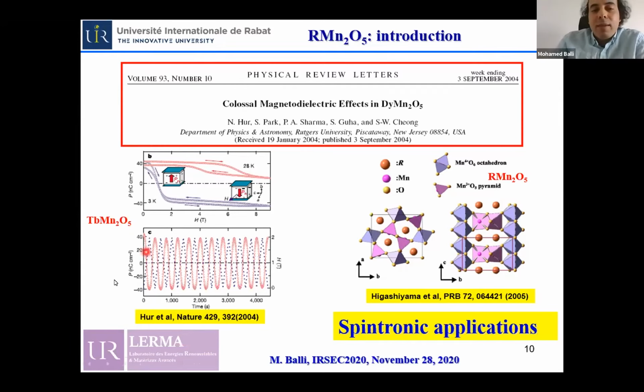For example, in this famous work published by Hur and co-workers in Nature, it was clearly shown that the electrical polarization of the terbium compound can be easily switched not by using electrical field, but by using a relatively low magnetic field of about 2 Tesla, opening the way for the implementation of this family of multiferroics in spintronic devices. So this is very important.